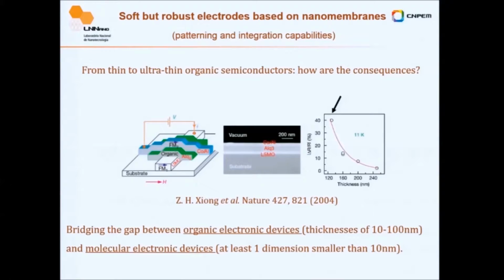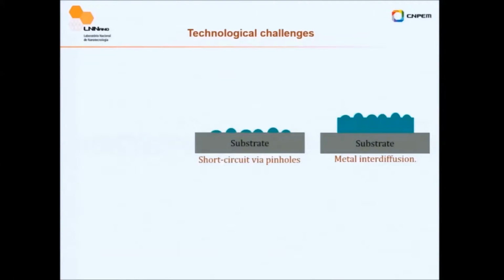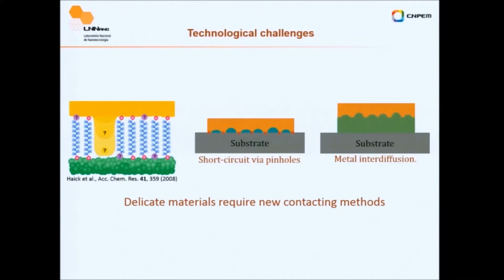It's well known, there are a few problems in this case. First, if you have a very thin film, you can form clusters, then you have a pinhole. And then if you make the deposition, basically you have a short circuit here. Another problem, you can even have a continuous film, but depending on the thickness, you have interdiffusion of metallic atoms that ruins your results in the best case. Haick et al. basically summarize the main problems. At first, if you have a junction, you never know if the conduction comes from pinholes. Because of the thermal energy during the deposition, you never know how your bonds end up. So making top contacts in organic devices is a problem, and it's still a problem.